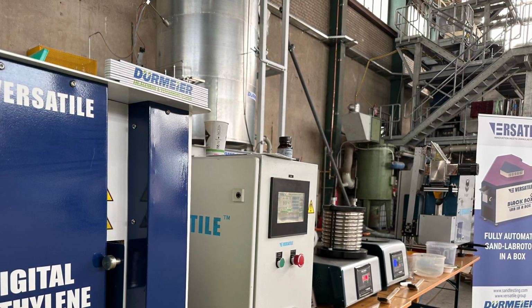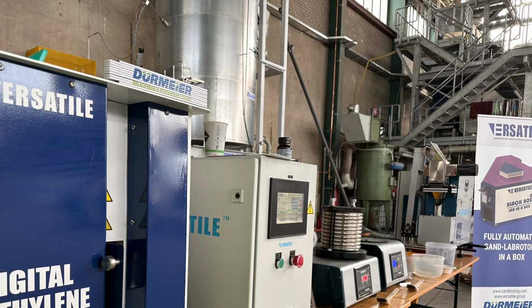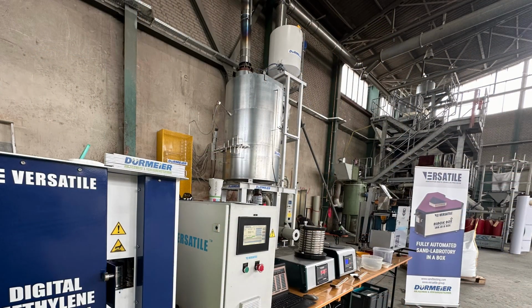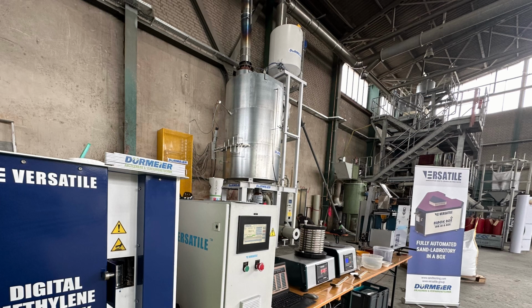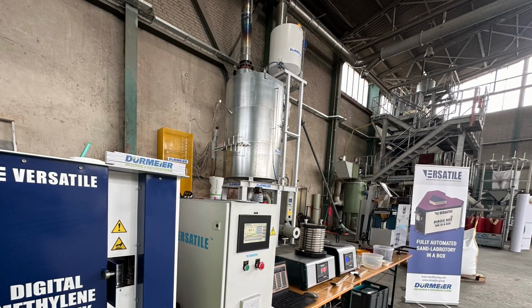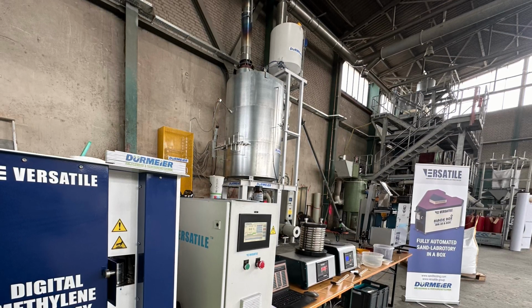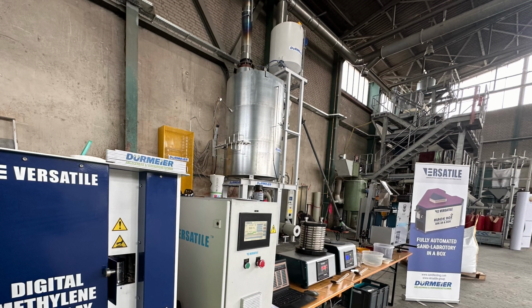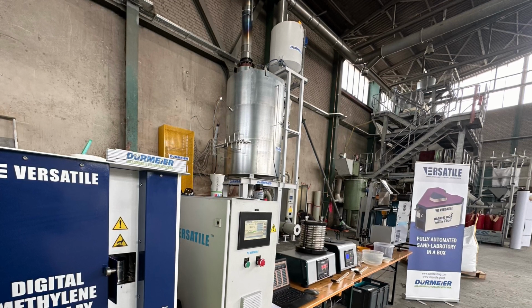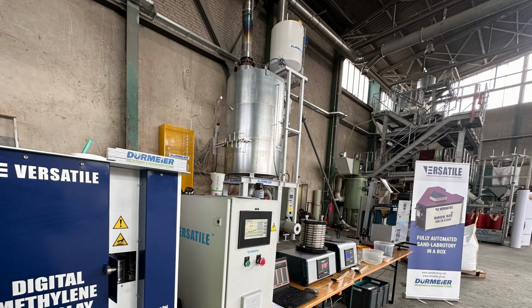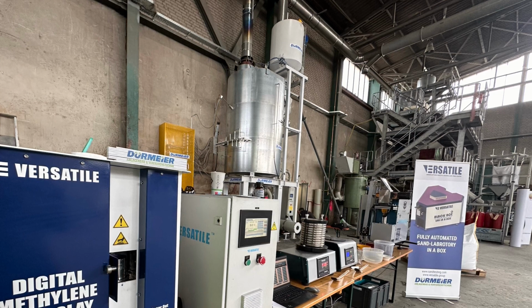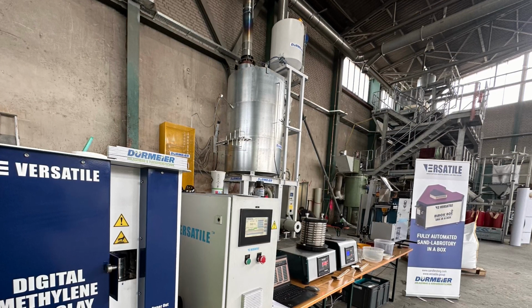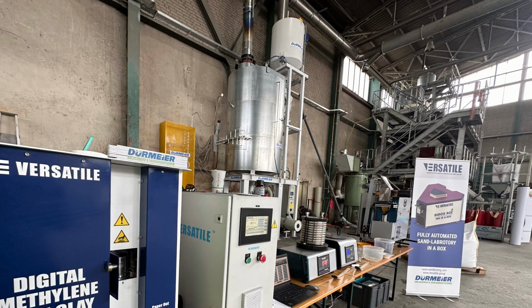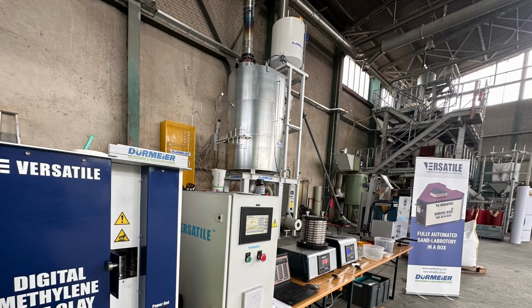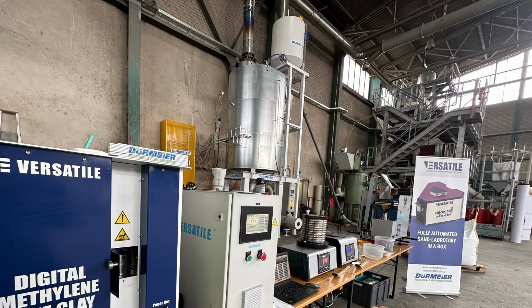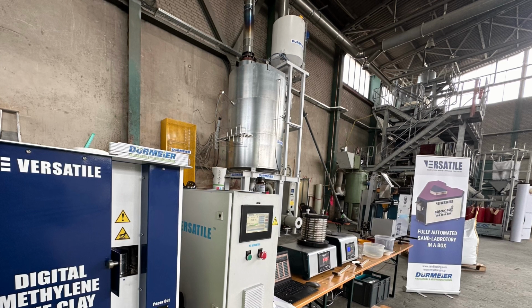Okay, so moisture and binder checked. What about testing the strength itself? How's that done? There are standard tests for that too. They measure the sand's strength when it's green, moist, and also when it's dried. Things like shear strength, splitting strength. Shear and splitting. What does that tell you directly? It directly tells you how well the sand will resist being pushed around or pulled apart. So its ability to hold the mold shape against the force of the metal. It's your main defense against those drops we mentioned, or the mold walls collapsing. Higher strength generally means a tougher mold.